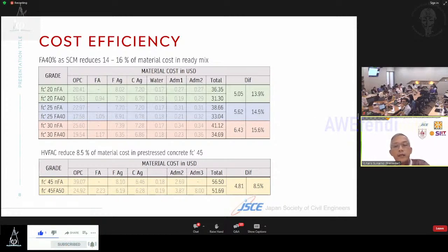And the second table shows the comparison on the high volume fly ash concrete that we use for the precast sheet pile. We can reduce about 8.5% of material costs in pre-stressed concrete FC 45. When we use FC 45 without fly ash, the total material cost is 56.5 US dollars. But for FC 45 with fly ash 50%, the total material cost is 51.69 US dollars. So we can save about 4.8 US dollars, or about 8.5% of total material cost.